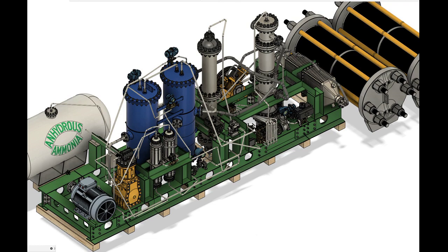More on iron ammonia synthesis catalysts. In the 1980s, Huazhong Liu and other Chinese researchers discovered a new high-activity ammonia synthesis catalyst based on wustite as a precursor in place of magnetite, the oxidic promoters being substantially the same. It was shown that the reaction rate of the new catalyst is 30 to 90% higher than that of the traditional one, and that such an activity difference increases when temperature decreases, as occurs with ruthenium. Resistance to sintering and mechanical strength are reported to be the same as the traditional catalyst, while resistance to carbon monoxide impurities is higher. The overall ammonia productivity increased significantly.